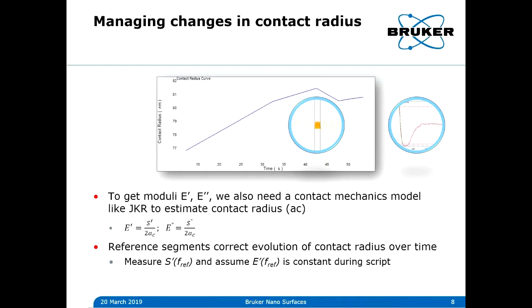And Bede, I would just add that what you're saying really applies to most AFM-based methods. Right, it's really contact area, which is a function of the tip radius and how much you're deforming into the sample. So even when you have regular tapping mode imaging with conventional sharper probes, how much that tip will sink into different materials, depending on their modulus, will ultimately affect the resolution as well. So it applies, I would say, even more broadly. Yes, right, definitely. Yeah, thank you.